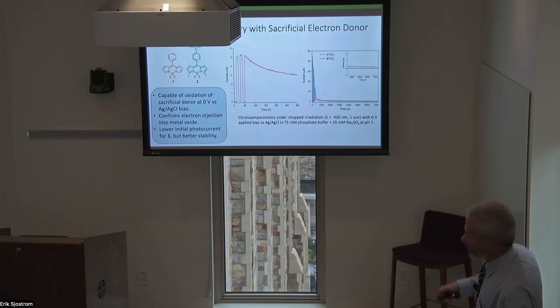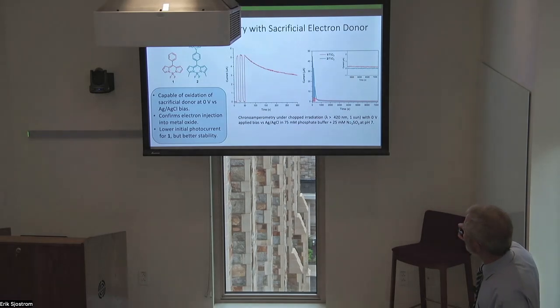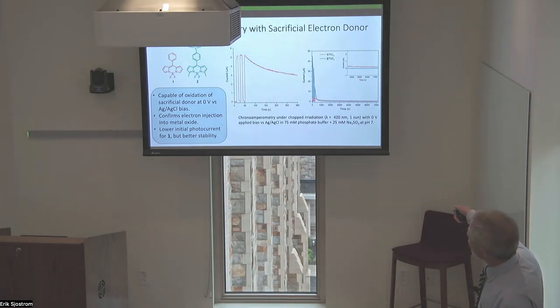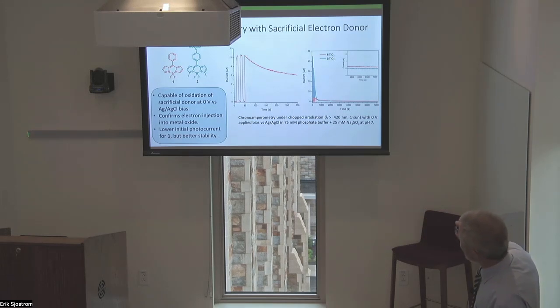This is sodium sulfite. Sulfite is an electron donor. And we can see a photocurrent, light on, light off, as the sulfite is being oxidized. This is just comparing a Brudvig molecule with the carboxylic acid version. They both show photocurrent, but you can see that the Brudvig is much more stable. Although it starts out with a lower photocurrent, its stability is higher and it's not decaying significantly. The carboxylic acid version decays quite rapidly, mostly because of dissociation from the surface in water, but also from faster degradation. So this is something that's very promising.